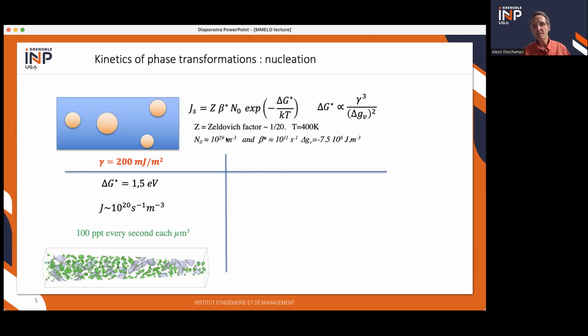So if you take typical values of the different parameters of this nucleation rate, and you take a 200 millijoule per square meter interfacial energy between the precipitate and the matrix, in these conditions, it gives you an activation barrier of something like 1.5 eV. And this will translate into a nucleation rate of about 10^20 per second per cubic meter. So it means that you will nucleate 100 precipitates every second in each cubic micrometer, which is a very large amount and which will help you having a very, very dispersed distribution of particles.